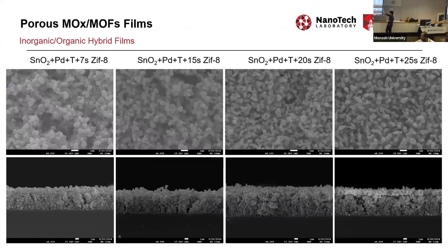This one at the bottom is cold welded. We have the tin oxide, then we cold welded it. That's why it is not as porous as you would see in a flame-made film. Then we added zinc oxide on top. We didn't cold weld the zinc oxide, but we changed it into ZIF8. Yes, you do have that flexibility of multiple layers. You can go up to as many layers as you want, do all the processing you want on the bottom layer, and then see what you can do on the top layer. Once you do this cold welding on the bottom layer, to my understanding, that is not going to change anymore. That's very solid. The next process is not changing it. So you can create that one, then add the second layer and do whatever you want on the second layer.